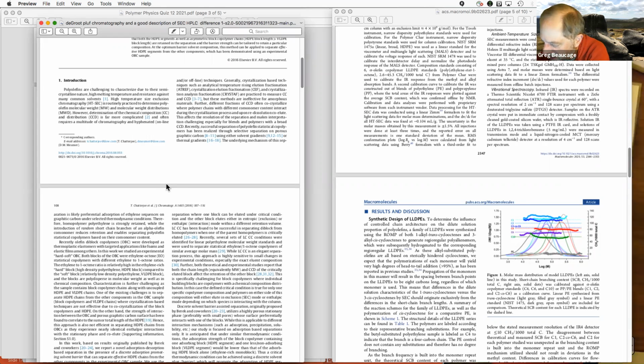This high pressure liquid chromatography relies on, as the polymer is flowing through, it having chemical interactions with whatever's in the column. So the things that have more chemical interaction go through slower, and it doesn't matter the molecular weight. Right, so liquid chromatography is enthalpic. It's like interactions. So you have these two kinds of chromatography that basically look exactly the same. They are the same machine, but basically it's got an entropic part, which is this size exclusion characteristic, and an enthalpic part, which is the liquid chromatography part. Right, so you could separate on both ends.